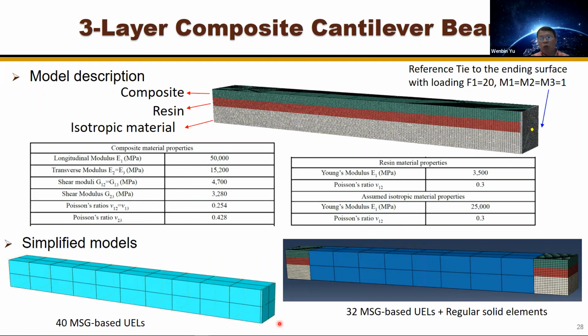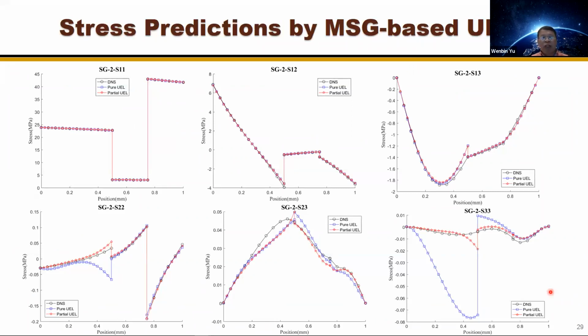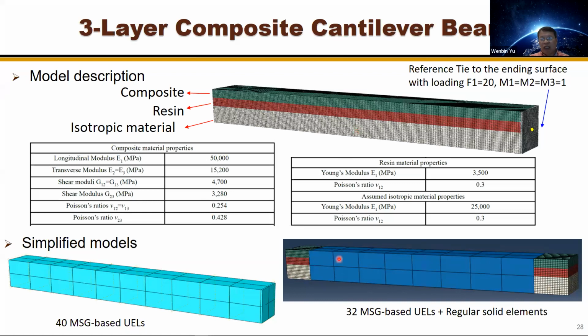And we know that when we do this homogenization, usually we cannot handle the boundary very well. What we can do is keep the boundary still using the original discretization, and only the middle part I will replace with this new user element. And now I have 32 MSG-based user elements and also these regular solid elements. If you look at the results for this problem, we did a DNS, which meshes everything with a very fine mesh. Pure UEL means 40 UEL elements. Partial UEL means at the two ends you have the DNS part and in the middle, this is partial UEL. The results I take are here, very close to the boundary. Actually, if I take it right at the boundary, then they are the same. But for pure UEL, they would be very different.